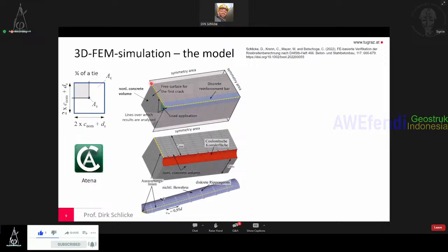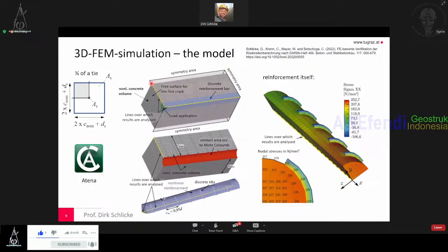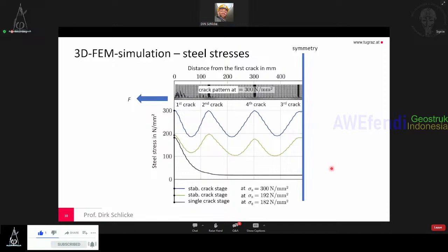If you look into it, you can see there's this nonlinear concrete volume. We have a nonlinear reinforcement element, discrete ribs on this. The contact area between the both is a Mohr-Coulomb law, and the lines over which results are analyzed are plotted here again. The reinforcement itself is also 3D, including the ribs, even included that the ribs are not going around the entire bar. If you look at results, you see in this quarter modeled, if you pull on the reinforcement,